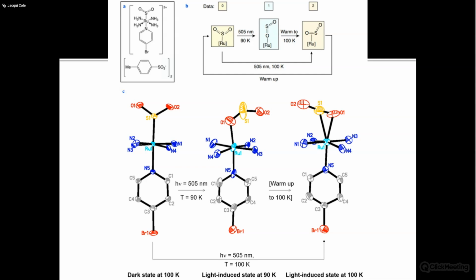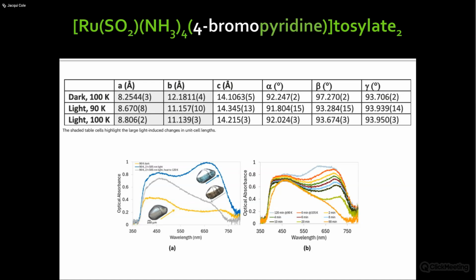So this is the first ever time I've had it so that you could isolate the dark state and the light state in both of the photo-induced configurations. That could be potentially useful. It's so clean optically from a photonic perspective. That's sort of a 0, 1, and a 2, right? So that's quite cool. It's also very clean in terms of the optical spectroscopy, because we've always had an insight into which part of the optical absorption belongs to which photoisomer and the dark state, but this is really clean, so we can literally say that this is definitely the optical absorption characteristics of the dark state and this isomer and that isomer. So that's quite helpful.